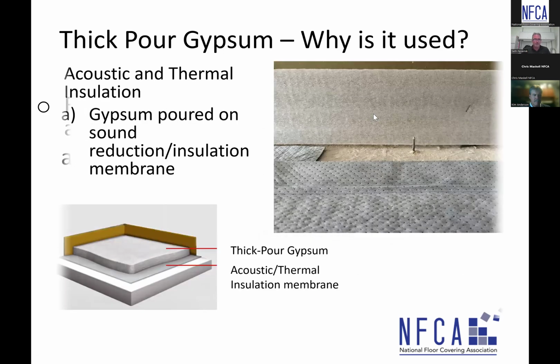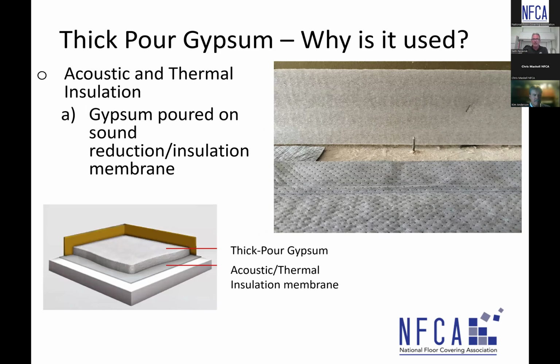Thanks. Yep. Another reason that thick pour gypsum is used is from an acoustic and thermal insulation standpoint. Sound reduction. You get into multi-family housing, a lot of times they have a membrane that goes down on the subfloor first, an acoustical membrane, and then thick pour gypsum is installed over top of it at a minimum of 3/4 of an inch and greater for that matter. In that type of application, the sheer mass of product, along with the acoustic or thermal insulation membrane underneath, provides added sound and insulation properties.